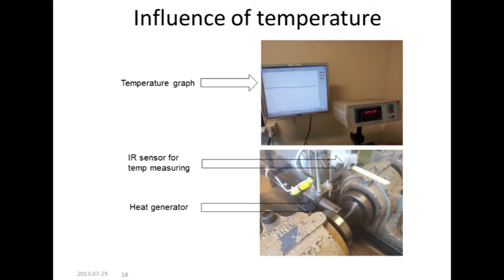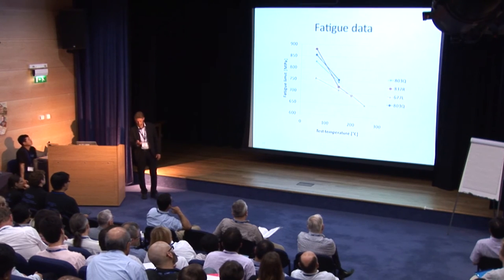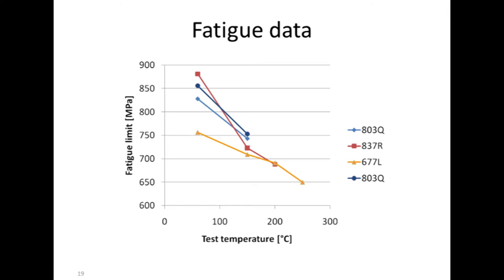The last is the influence of temperature, which I think is new and what we think is quite interesting. We have retrofitted machines making fatigue testing at elevated temperatures. So I will more or less end with this one, which is really looking at what happens. And the interesting thing is not the absolute number here, because the absolute number in many cases represents the steel cleanliness, but the slope that we see here.